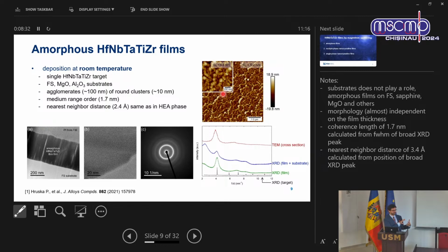That means that the atoms lose coherence after a distance comparable with 5 unit cells of the crystalline material. However, from the position of the amorphous peak, you can see it correlates well with diffractions of a crystalline target. And it's really at the same number, which corresponds to the same nearest neighbor distance. So this is already some indication that this amorphous phase can eventually be used in further studies.